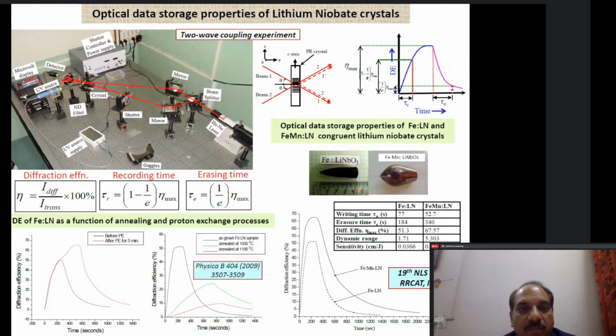So here what we do is we make one beam split into two beams, and these two beams are then made to interfere inside the crystal. For example, what you see here, beam 1 and beam 2 are coming and they are interfering inside this. And because it is a photorefractive material, photorefractive means you can change the refractive index of the material using photons, right? So lithium niobate is a photorefractive material.